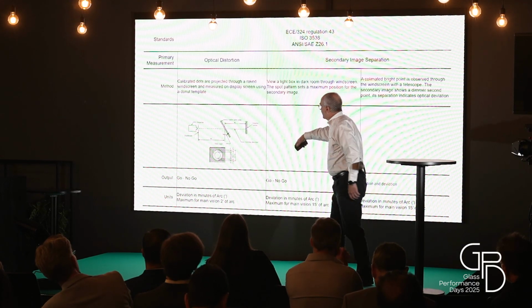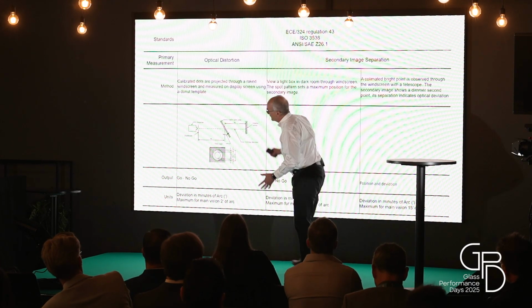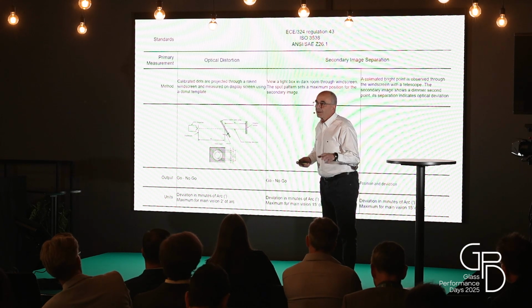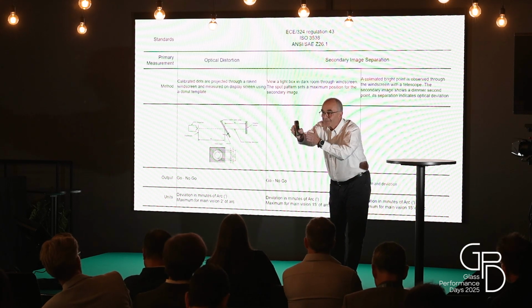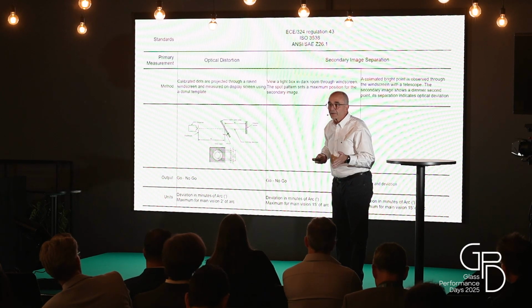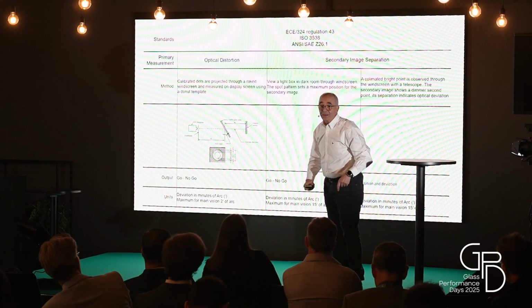And depending on your geometry, the size of the dots, basically the standard deviation in the automotive industry is 2 minutes of arc. So it means that the light will not deviate more than 2 minutes of arc. That's for a football that high. It's about 700 meters away.